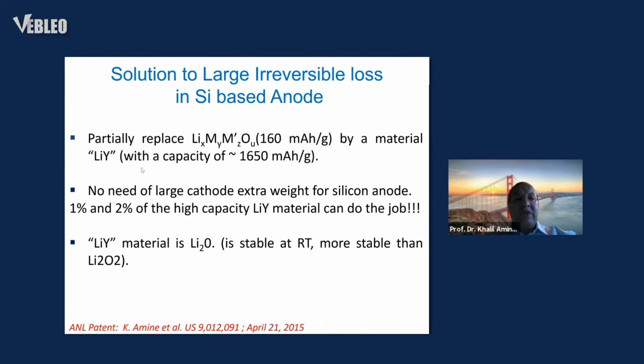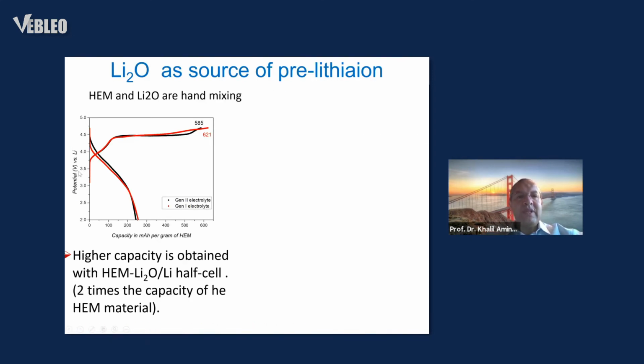So we used, for example, lithium oxide, because this material has very high capacity. We can use 1 or 2% on the cathode and activate it and send the lithium to the anode. Very simple process. The question is how you can activate this material. Are they compatible? Are they stable in the presence of this cathode, and so on? So here is an example.